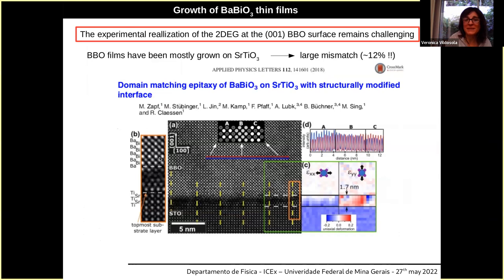Then, well, the experimental realization of these 2D electron gases at the surface of this material remains challenging. There was a paper reported that the problem is that when you have such a large mismatch between the material and the substrate, you have some reconstruction of the surface that cannot be single terminated. So we cannot have a clean bismuth terminated surface for this film. So I was kind of disappointed, because I was about to give up this research line, to be able to see the realization of this DFT prediction.